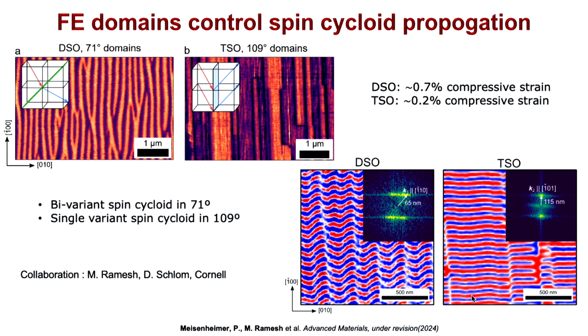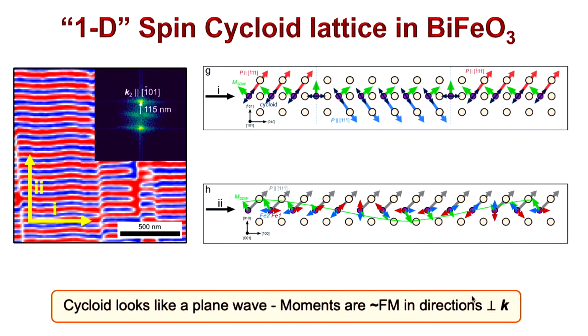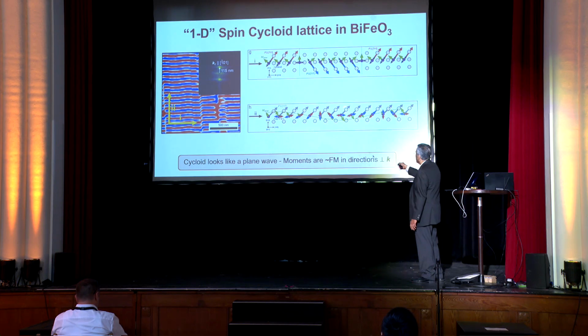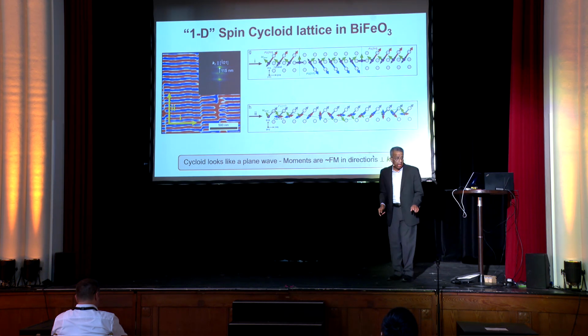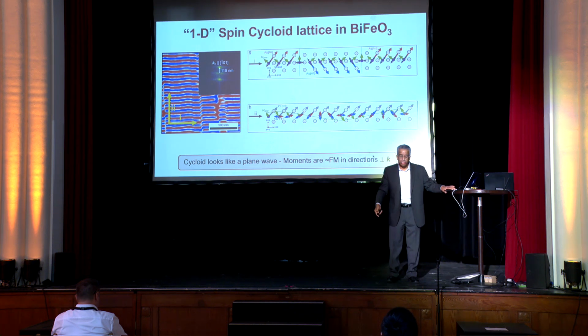If you now go back to exactly the same samples and do the NV imaging, you can start to see the chevron-like pattern, while for the terbium scandate, it forms a single variant, almost like a lattice. And that single variant has the cycloid that looks like a plane wave. If you go along this direction, which is direction 1, you can see that the green arrows are approximately all in the up direction. While you go this way, the green arrows are going up, down, up, down, up, down. And so you can actually start to create a reasonably ordered lattice of the spin cycloid.